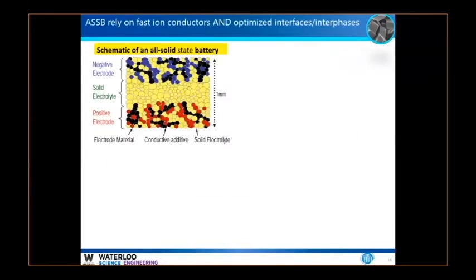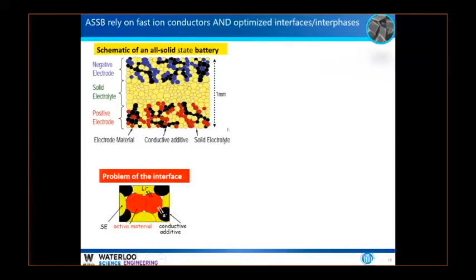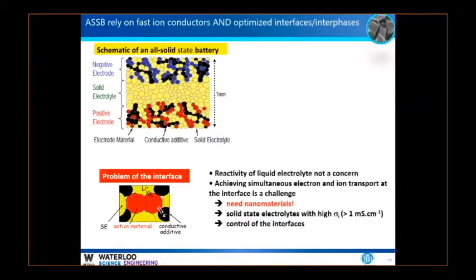So they work sort of like a typical liquid cell, except that instead of a liquid electrolyte, there's a solid electrolyte. And this solid electrolyte is mixed with the positive electrode material at one end and maybe the negative electrode material at the other. So instead of having a liquid permeate this porous structure, now we have to have a solid permeate this solid structure. And so that leads to what we call problems of the interface, namely that lithium ions and electrons have to get to this positive electrode material simultaneously. So while the reactivity is not a concern, achieving simultaneous electron and ion transport at these interfaces is a challenge.